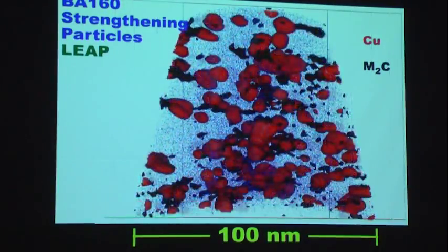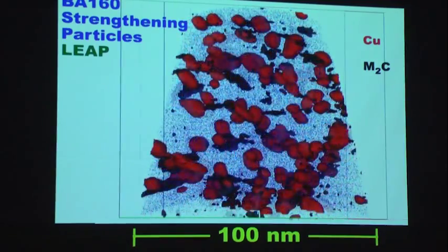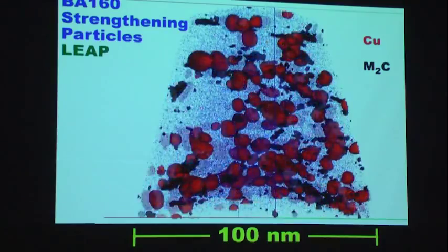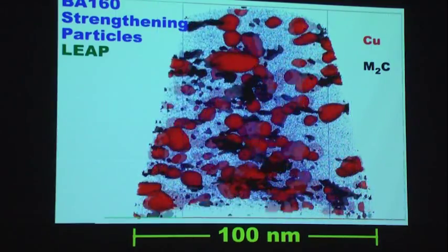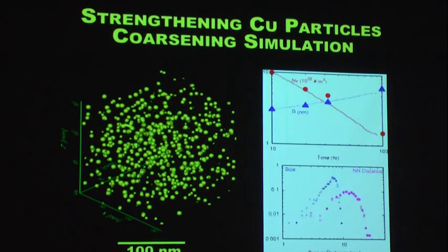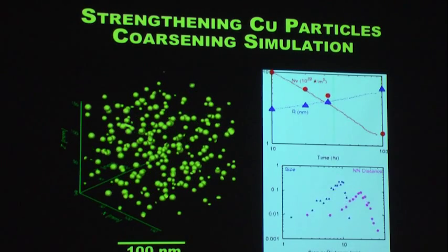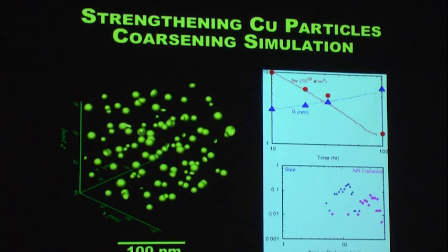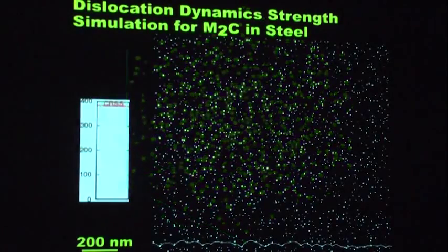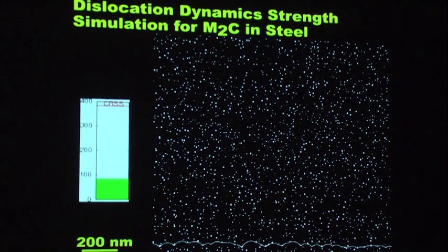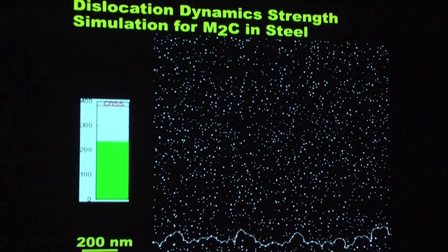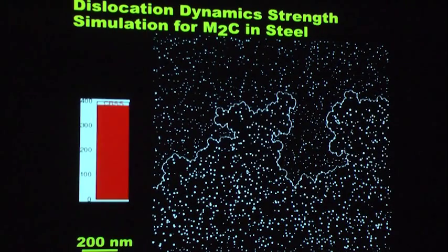Now, zooming in down to the local electrode atom probe, this is a reconstruction of the nanoscale copper and carbide strengthening dispersion in a blast protection steel that we designed for the Navy. The new information this is giving us that we didn't have before is the spatial distribution of these particles. We're simulating that now for the coarsening of the copper particles in a 3D simulator that allows for the diffusion field overlap. And then we're taking statistically equivalent spatial distribution of these particles, putting that in a dislocation simulator, and measuring now the impact on strength of these new attributes that we're getting from tomography that we didn't have before. So to get greater accuracy out of our strength models by taking this into account.